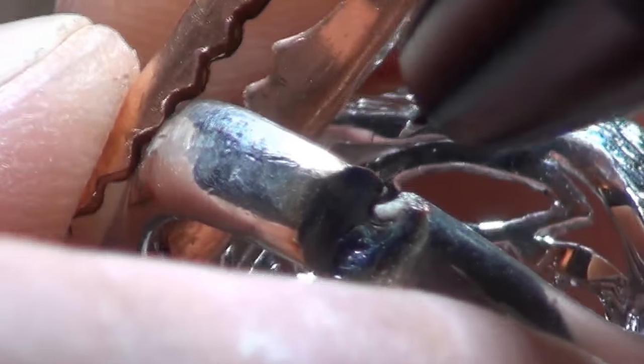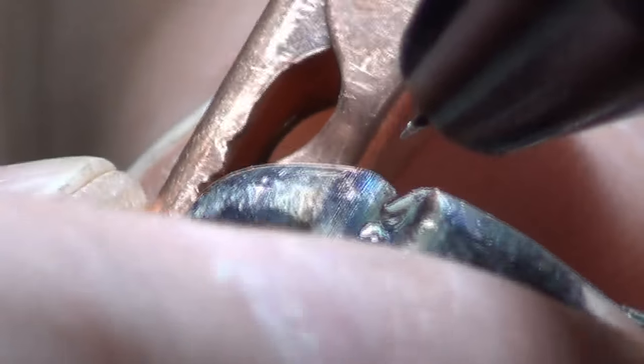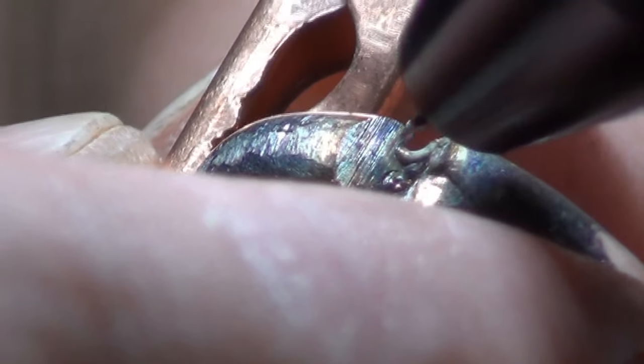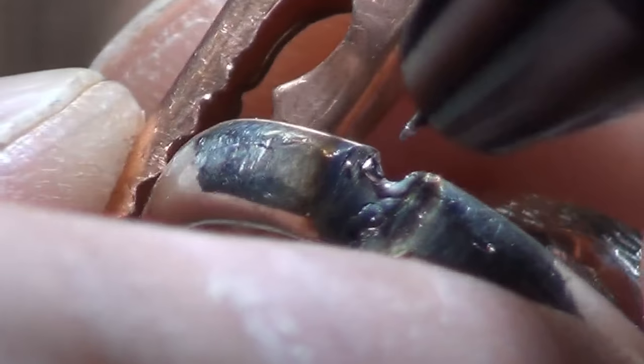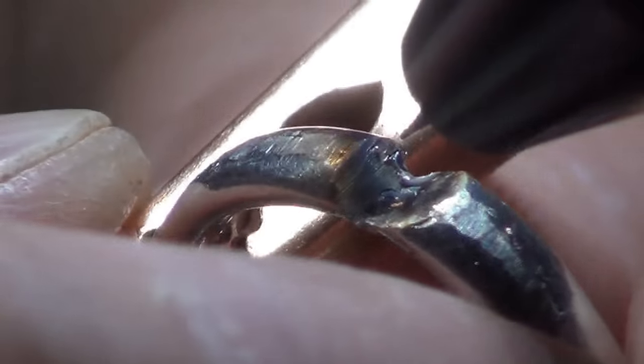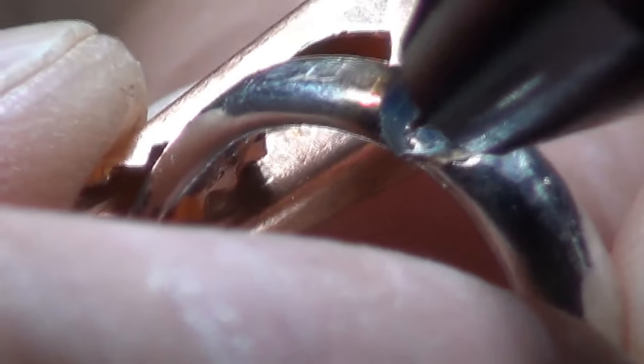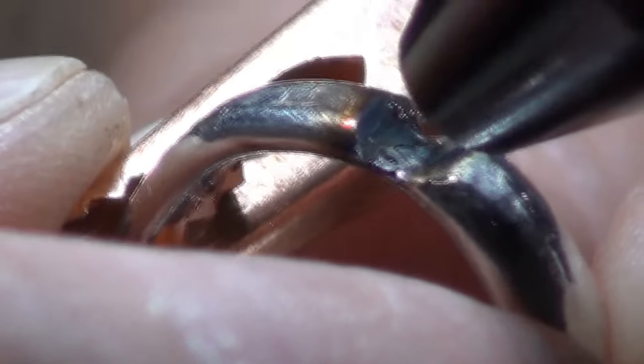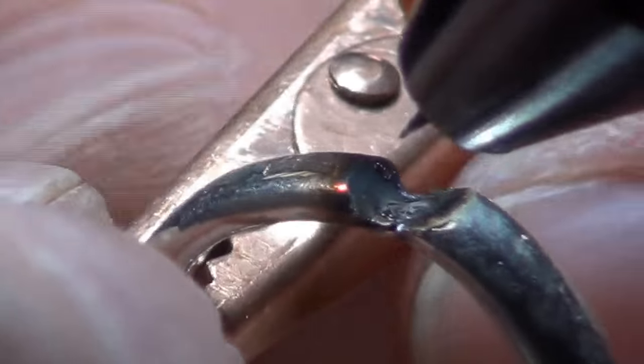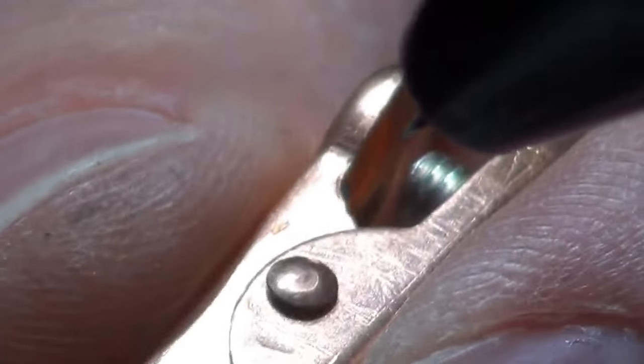You can see there that where the material is really thin, it actually kind of pulled it across, and that's okay. We're not too worried about it because we're going to come back and add it again. So you can see I want to kind of create that gouge a little bit, but I'm just making sure I'm spreading it across that weld joint. Now when you're working with silver, silver welds better warm than it does cold. And so you want to try and avoid stopping as much as possible, and specifically stopping for no reason if you don't have to.